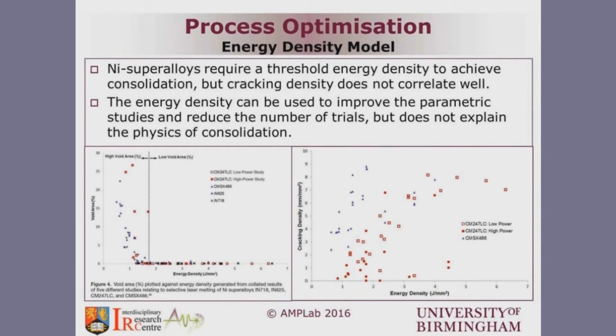But that correlation did not hold, as I mentioned, when it came to cracking. We still had an increasing trend of cracking density with increasing energy density, but there was still some scatter in the data, suggesting that this model may be good enough for looking at porosity, but not the best when it comes to cracking density.